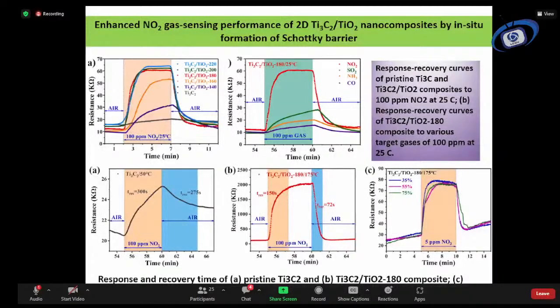Similarly, we see the maximum response was gained at 180 centigrade for nitrogen dioxide. And you can see when air is purged, when air is input for the first time, the resistance goes up, and then gradually decreases as well. So we can see there is a time of recovery and a time of response in figure A at the bottom. The response time and the recovery time are very large, 300 seconds and 275 seconds. As I said in my initial two slides, all parameters cannot be satisfied at the same time. So we try to control some parameters and get a specific output for a specific sample. And in figure B, you can see it has been decreased from 150 seconds to 72 seconds.